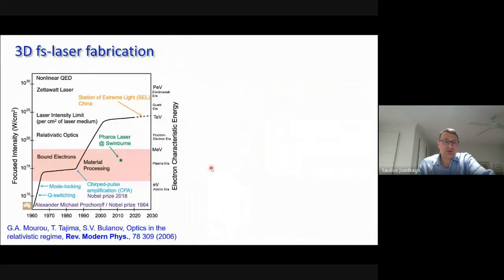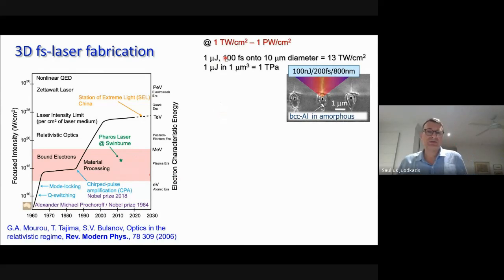So this is the same plot which we saw already in the series of seminars here. If we look at intensity, how it has evolved over the years, chirped pulse amplification starts at this point. And this is driving intensities to the high frontier of new science. At the same time, for material processing, we are very fine in this window, which is around 1 terawatt per square centimeter intensity per pulse to 1 petawatt. So this is 3 orders of magnitude, but this is where we can do basically anything with very different materials in terms of how we can modify them.